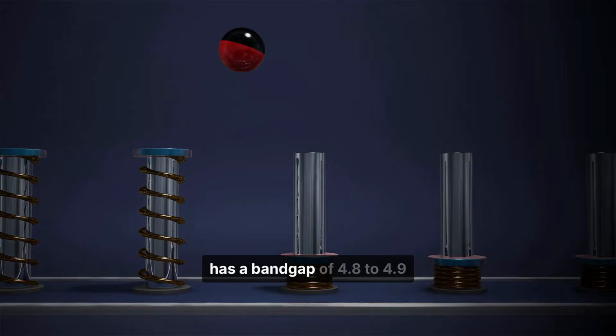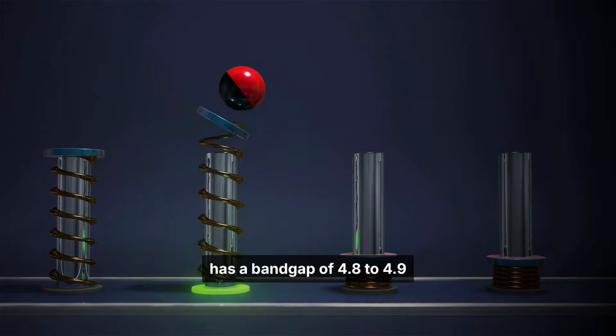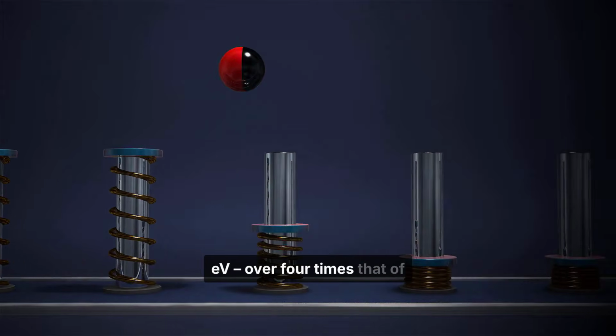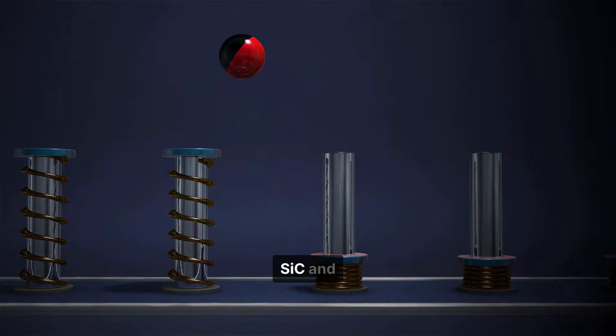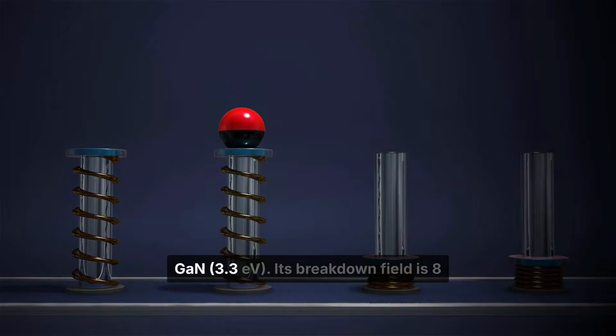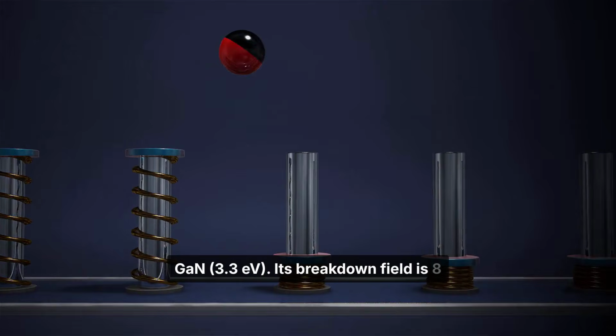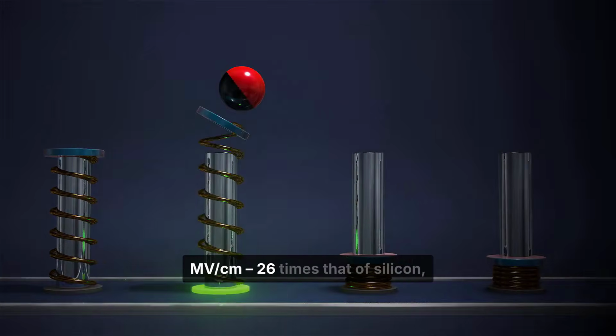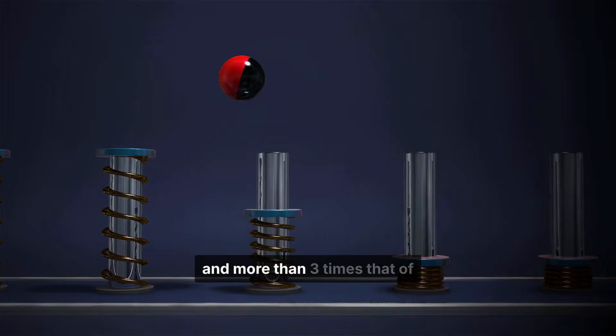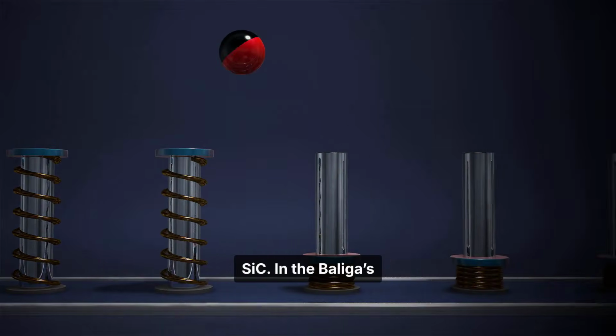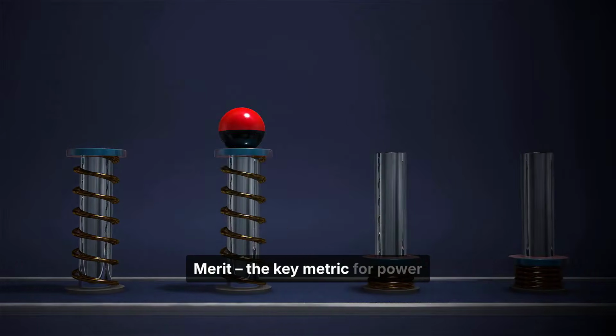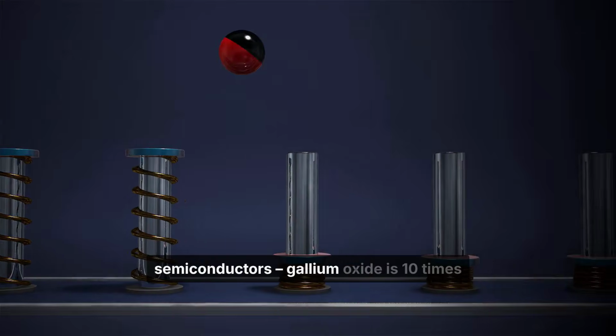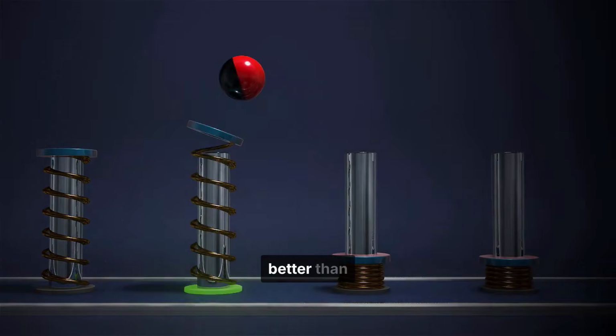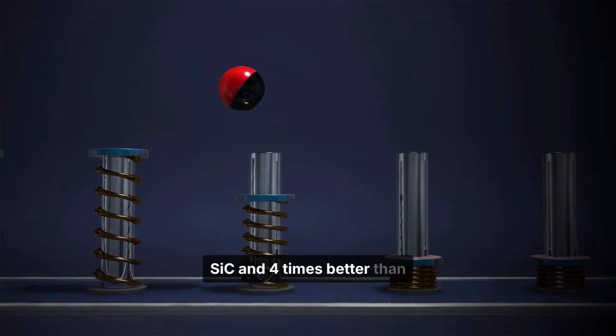Gallium oxide has a band gap of 4.8 to 4.9 eV, over 4 times that of silicon and well above SiC and GaN, 3.3 eV. Its breakdown field is 8 MV/cm, 26 times that of silicon and more than 3 times that of SiC. In Baliga's figure of merit, the key metric for power semiconductors, gallium oxide is 10 times better than SiC and 4 times better than GaN.